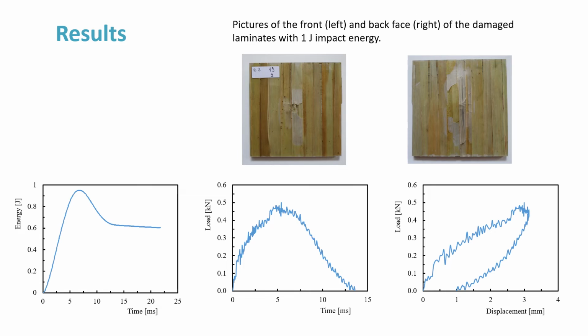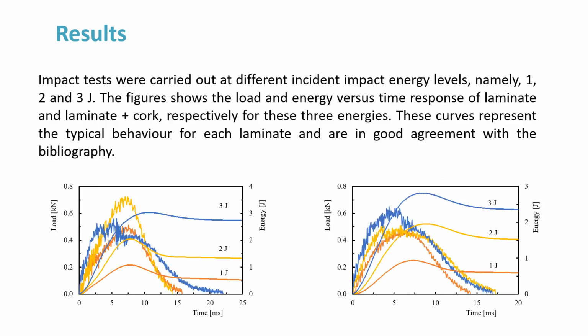The figure shows the energy versus time, load versus time, and load versus displacement curves for laminates. These diagrams represent a typical behavior that occurred for all laminates. Impact tests were carried out at different incident impact energy levels, mainly 1, 2, and 3 joules. The figures show the load and energy versus time response of laminate and laminate plus cork, respectively. For these three energies, these curves represent the typical behavior of each laminate and are in good alignment with the bibliography.